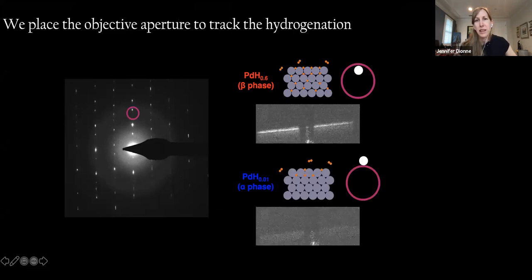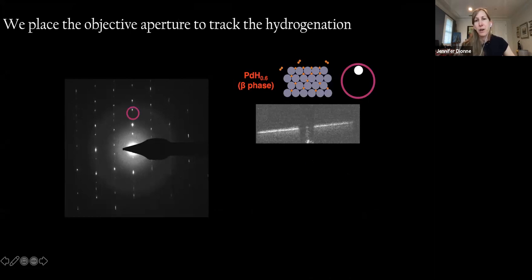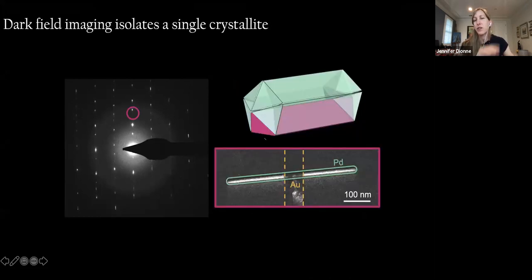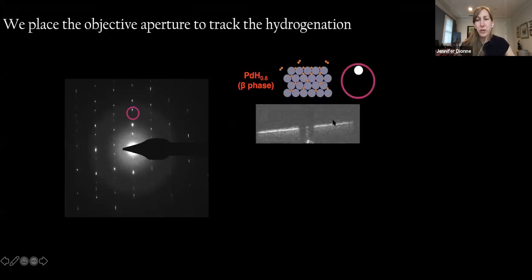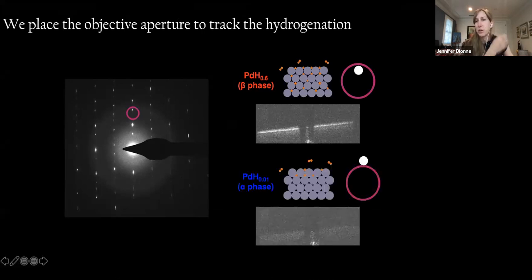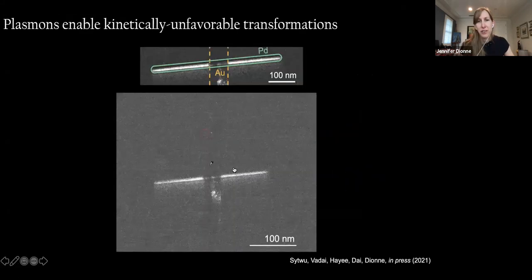So when we're in the beta phase, the crystallite that we're going to be looking at is the one that's actually going to be, as you can see here, closest to the gold bar. So that crystallite will be lit up or have bright contrast when we're in the beta phase, and it will appear dark when we're in the alpha phase.